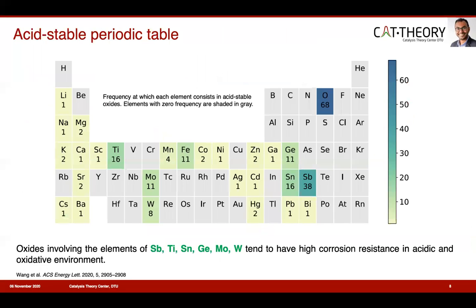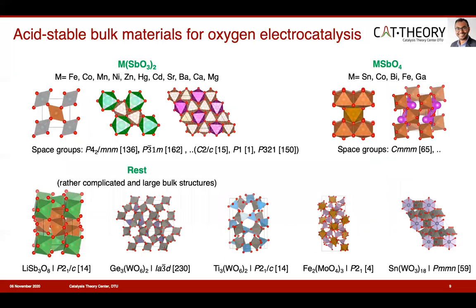Based on the composition of the 68 materials, we construct an acid-stable periodic table. From this periodic table, we clearly observe that antimony, titanium, tin, germanium, molybdenum, and tungsten-based oxides prefer being stable in strong acids. Most of the acid-stable oxide materials are ternary oxides, and the rest are quaternary oxides. A closer look at the space groups of the materials reveals tetragonal, orthorhombic, trigonal, and monoclinic materials with various space groups, as you can see. Moreover, materials with a wide range of atoms in the bulk unit cells are observed.